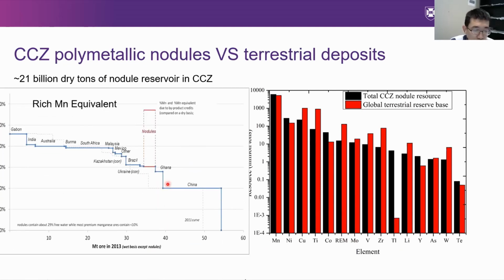So here, when we compare the manganese grade in the nodules with the standard land-based manganese ores, as you can see, because it contains some water, the manganese grade in the nodules is lower than the land-based manganese ores. However, if we extract the valuable metals and other ions, then the manganese in the nodules will be concentrated. So the manganese grade will be upgraded, and then it will be comparable or even higher than the manganese ore. So this will be a very good byproduct and give credits to the value of nodules.